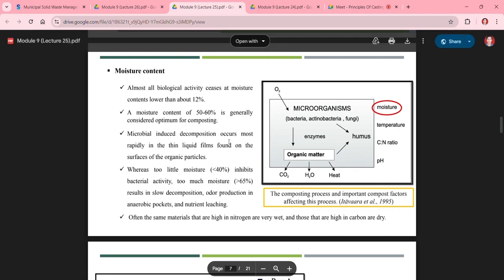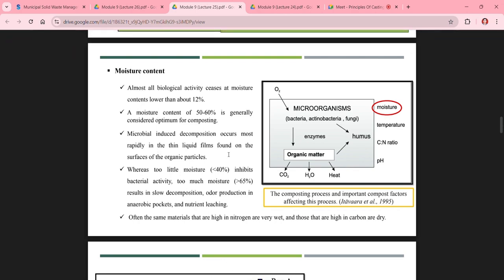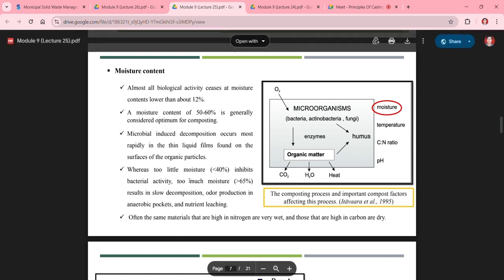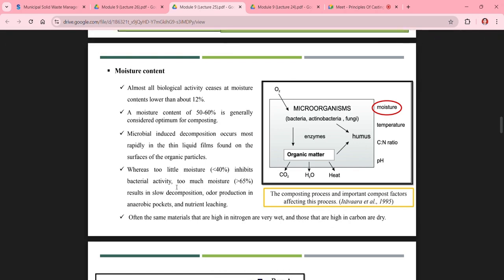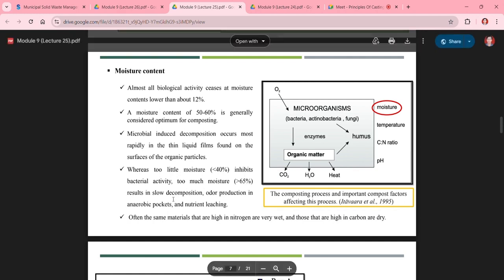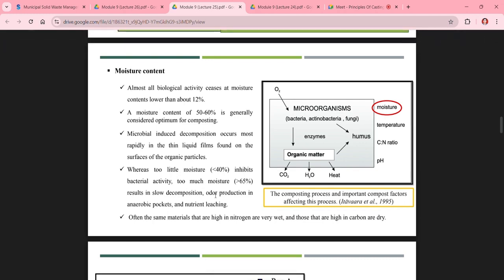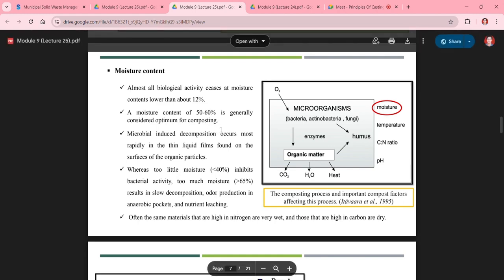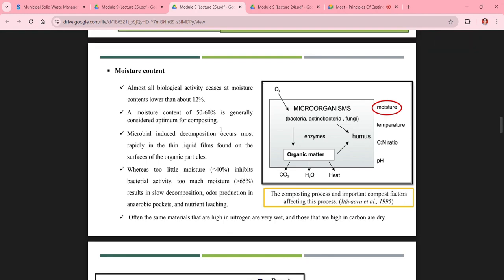Microbial induced decomposition occurs most rapidly in the thin liquid film found on the surface of the organic particles. Too little moisture, less than 40%, inhibits bacterial activity, while too much moisture, in short greater than 65%, results in slow decomposition, odor production in anaerobic pockets, and nutrient leaching. So we need a moisture content at around 50 to 60% for proper microbial action and to convert the municipal solid waste or kitchen waste into compost.